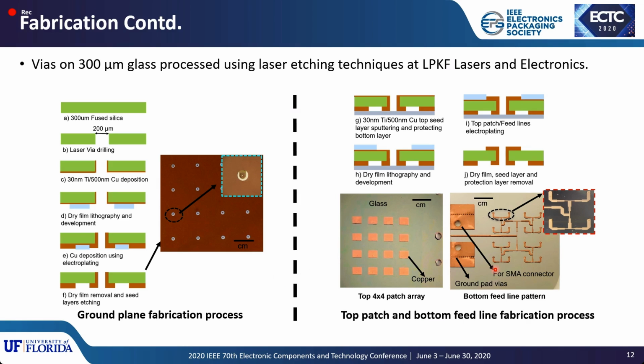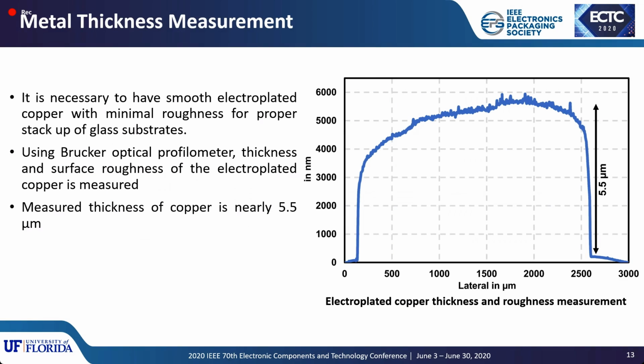While the top and the bottom feed lines are patterned, the bottom ground, or the top ground in the case of the second substrate, are covered with a protective layer in order to prevent the electroplating growth on the ground layer. Once the devices are fabricated, the total metal deposited during the electroplating process is measured. It is necessary to have a very smooth and uniform metal deposition on the glass substrate, because since we are stacking two substrates, it is necessary to have a very smooth interface between both the layers.